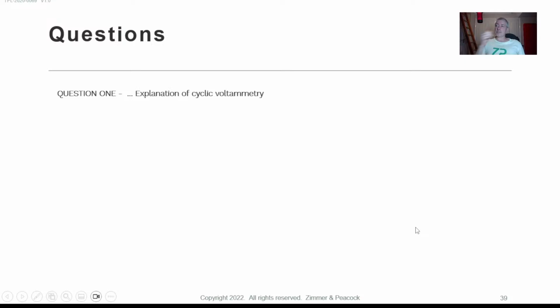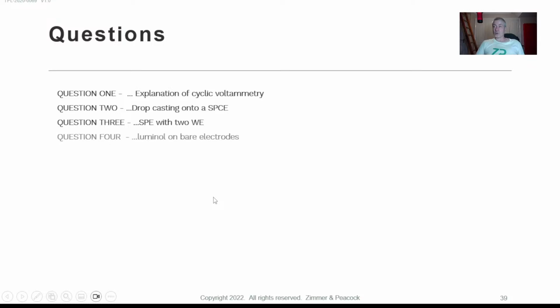So question number one, an explanation of cyclic voltammetry. I have a suspicion with your cyclic voltammetry, you're basically measuring oxygen as the source of that signal. I suspect that the aromatic compounds are sticking to your electrode and blocking it, and the hexane is actually washing away your polymer and exposing it, so you can increase the oxygen reduction. Drop casting onto SPEs, screen printed carbon electrodes, or SPCEs I should say, is quite straightforward now with that circular electrode. If you want two working electrodes, we can make it for you, but we would do it as a micro project.